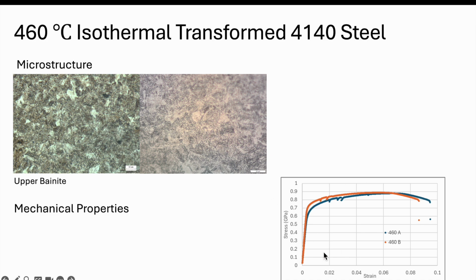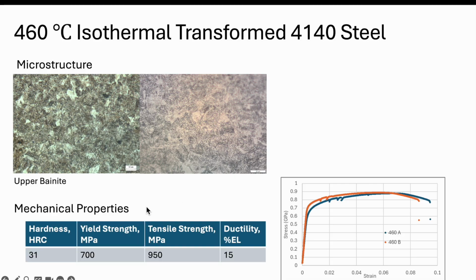So this is the engineering stress strain for a couple samples of 4140 steel that's been treated to 460 isothermally. From that, we see that the yield strength again has gone down to about 700 megapascals. Tensile strength has also gone down to around 1,000 or 950 megapascals, and the ductility keeps going up, right? We're getting more and more ductility from this, about 15% elongation. And the hardness has also gone down to about 30 on the Rockwell C scale.